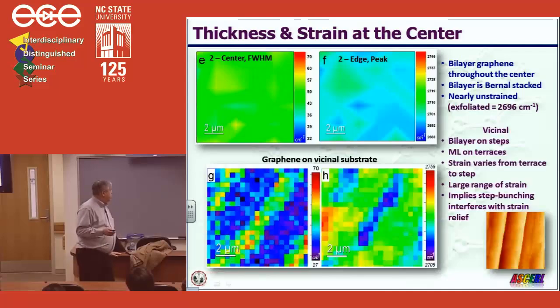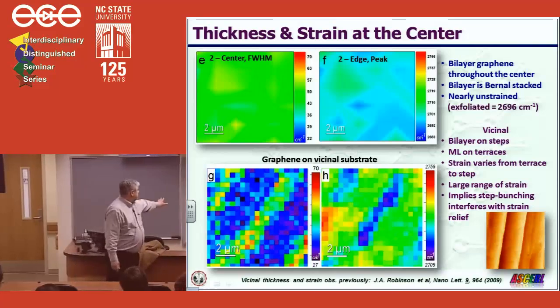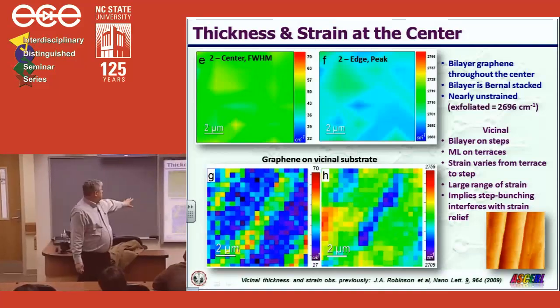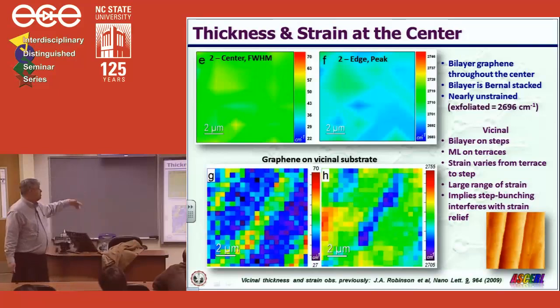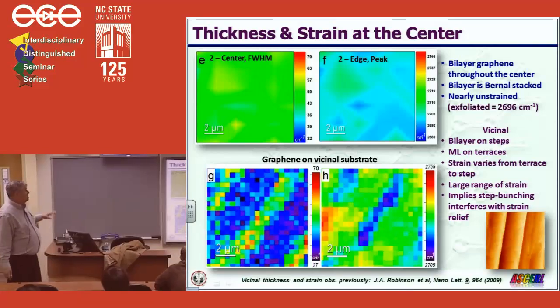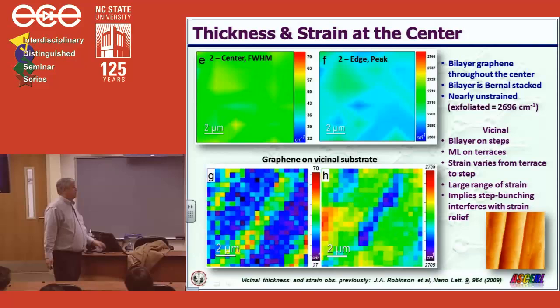And again, comparing it to the conventional substrate, which has this terrace and step morphology, you can see it's extremely different. These are both on the same scale. So this is what you would see with the step-free and what you see with the conventional. So this is very different in terms of its properties.